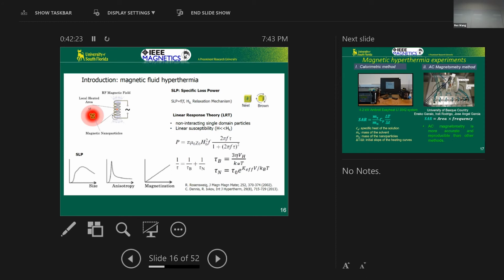Okay. All right. So now the simplest way to increase the SAR or the heating efficiency is to use particles that have the largest magnetic moments. You can see there's a simple linear dependence. So you increase the saturation magnetization of the particles that you're using, your SAR goes up. But it's easier said than done, because those of you making nanoparticles know that the magnetization goes down compared to the bulk. And this is because the surface is disordered, so really you cannot get bulk magnetization.